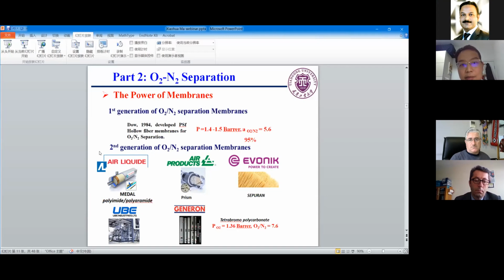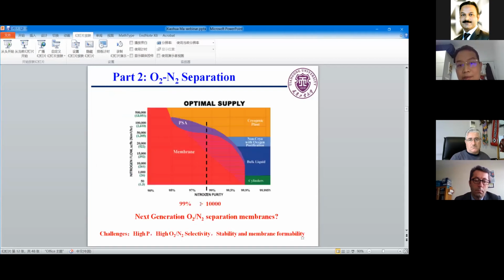And then in the 1990s, most companies reported the second generation O2/N2 separation membranes, like MEDAL, Prism, UBE, and Generon. The representative of these membranes is tetrabromo polycarbonate. The permeability of oxygen is about 1.4 barrer, almost the same as the first generation, but the selectivity increased from 5.6 to about 7.6. But even this slight increase in selectivity made it very competitive in generation of 99% nitrogen. At that time in the 1990s, almost 10,000 of these small units for on-site nitrogen generation were working worldwide.